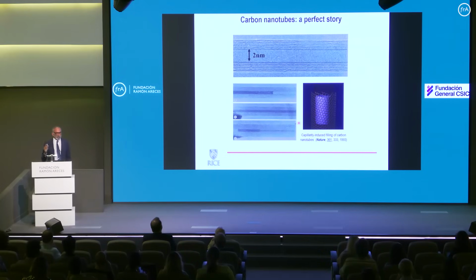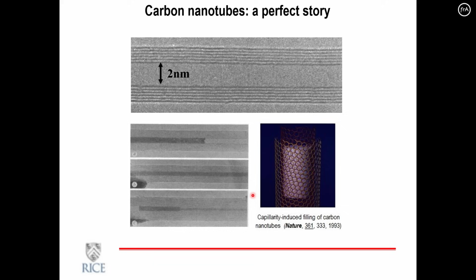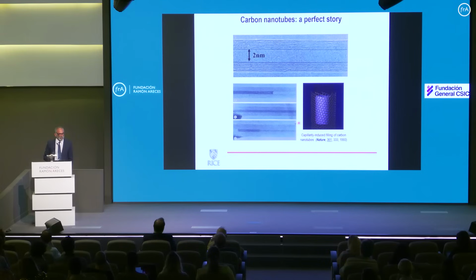So the carbon nanotube is really a perfect story. It was found serendipitously in a material that was derived from the carbon arc discharge, and Professor Sumio Iijima at NEC was looking, just as a microscopist, at a range of structures that were part of this soot generated from the electric arc. And he found these beautiful molecules or these fibers that were present within the soot that was surrounding it.